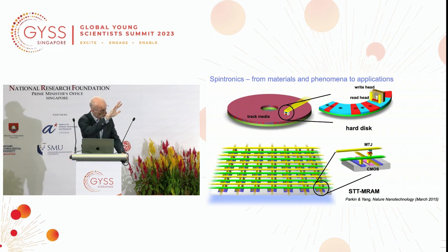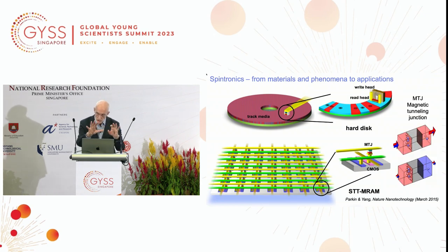And at the same time, if you look at the top, I remind you again, this is the magnetic disk drive. We incorporated the metallic spin valve into this recording device, which moves mechanically over the top of the surface of this magnetic layer at a distance today of about a few nanometers, enabling us to read the transitions between these magnetic blue and red regions with greater sensitivity than was ever possible before. It turns out this metallic spin valve was used in magnetic disk drives for 10 years, 1997 to 2007, and was then replaced by this magnetic tunneling junction using the materials that we proposed in 2004.